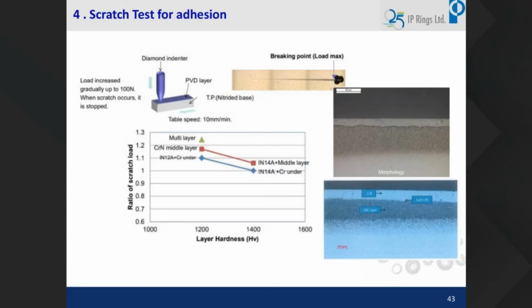The scratch resistance also is much better when compared to the ordinary IN14A chromium. This is the IN14A chromium undercoat, and this is the middle layer, what we call chromium nitride. It is nothing but a chromium nitride, but in a different stoichiometry. So subsequently we modified the PVD process, all our PVD recipes changed from undercoat to middle layer, and then we processed a few products, and this was again evaluated.